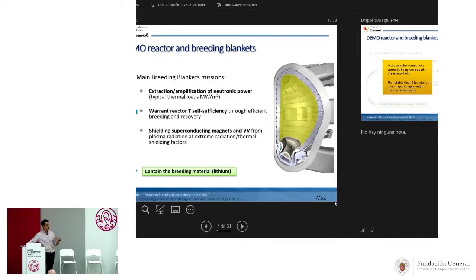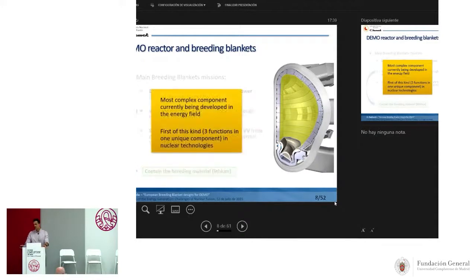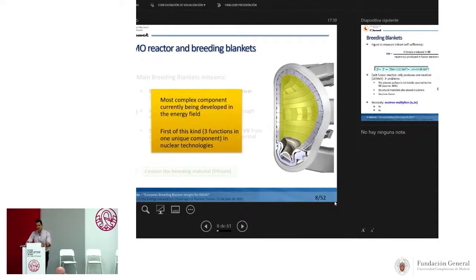Since we have to guarantee the tritium self-sufficiency, remember this word, self-sufficiency, we want to be self-sufficient with the fusion reactions. The blanket must contain the breeding material, in this case the lithium. And these three functions make the blanket the most complex component in the energy field. There are other components in other energy fields with some of these functions, but this is the only component that has the three functions in the same component, and this is quite important.